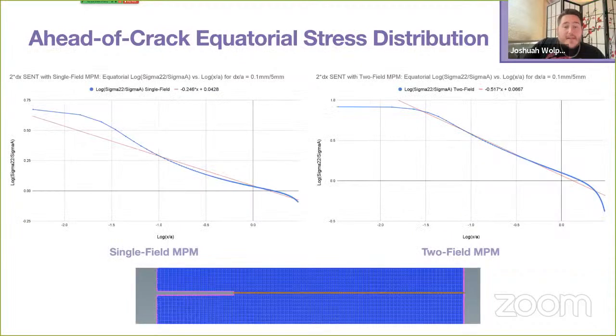So specifically, the second fracture mechanics result we expect to see for the SENT specimen comes from analytic relationships from linear elasticity that state that we expect to see a specific power relationship of the stress ahead of the crack tip as we move from the crack tip to the other free surface ahead of the crack. And you can see this region is highlighted in the image below here. But more specifically, if we plot the logarithms of our previous metrics, we should see a slope of negative 0.5. And the big takeaway here, as you can see, is that single-field MPM fails to produce this slope while two-field captures it quite nicely.